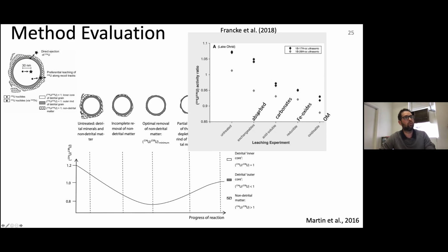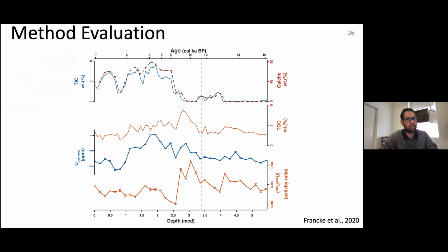So we do remove uranium adsorbed to mineral surfaces, carbonates, iron oxides, and then organic matter was actually a bit of a concern for a long time, because it's pretty tricky to completely and comprehensively remove organic matter from a bulk sediment composition. Hydrogen peroxide treatment is long-winded, and it's usually incomplete. So the question we had to look into again is, are there any controls by the amount of organic matter on our activity ratios, which would obviously not be an erosion proxy?